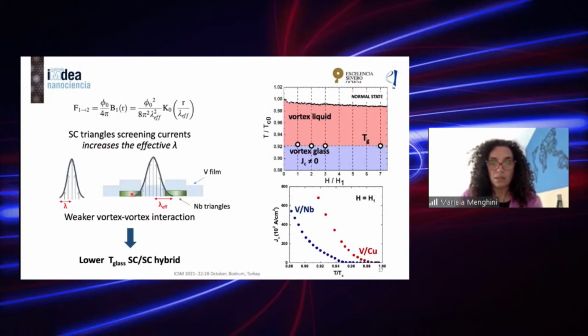So in our case, we argue that something the opposite happens. Now we have these superconducting triangles, and the screening currents that are circulating in these niobium triangles cause an increase in the effective lambda, and therefore a weaker vortex-vortex interaction in this system, and that can explain this lowering of the glass transition temperature.